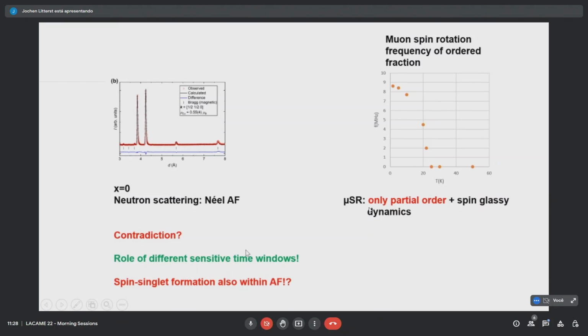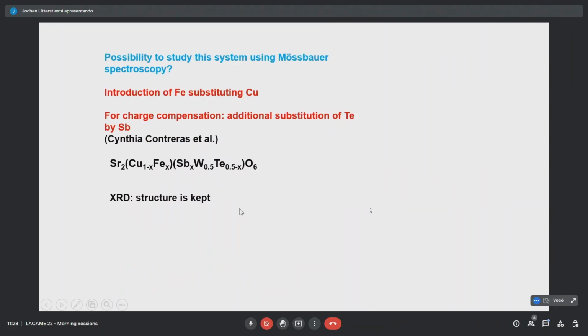So what does it mean for the interpretation that we see this superposition? That gives a hint that these spin singlets are not only appearing in this frustrated relation in between the two compounds, but even in part in the antiferromagnetic range for x equals 0. So it's extending into the antiferromagnetic range.